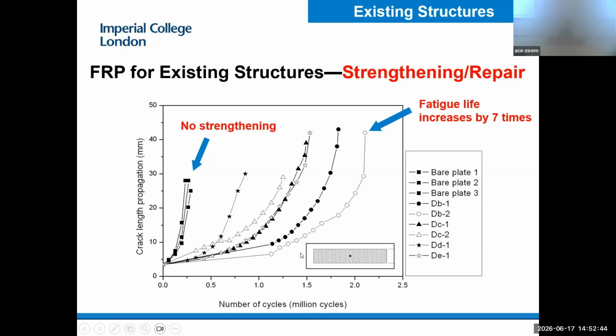So this is the specimen that gave us the best result. The width of the steel plate is 15 centimeters, and if we use a 10 centimeter wide FRP covering the center crack, we can increase the fatigue life by 7 times. If you cover the whole surface of the steel plate, we can achieve an infinite fatigue life - that means the specimen doesn't fail after 2 million cycles.